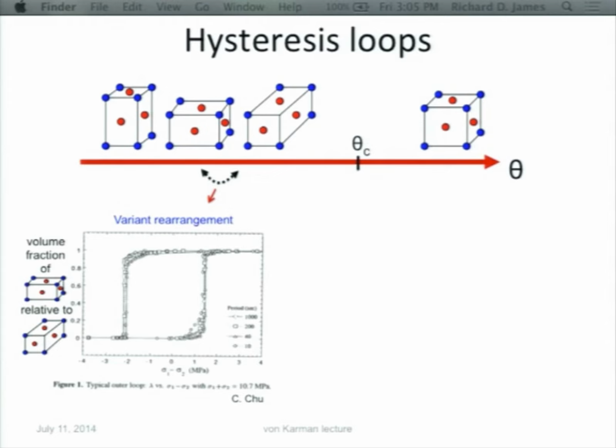So this is a phase transformation between a cubic phase and a tetragonal phase, one of the most simple kinds of phase transformations, where this cube at a certain temperature, theta C, distorts by elongating along one direction. And there are 3 possible symmetry-related directions, so you get 3 so-called variants of the low-temperature phase. The terminology: this is martensite, and this is austenite, and these are the 3 variants of martensite.